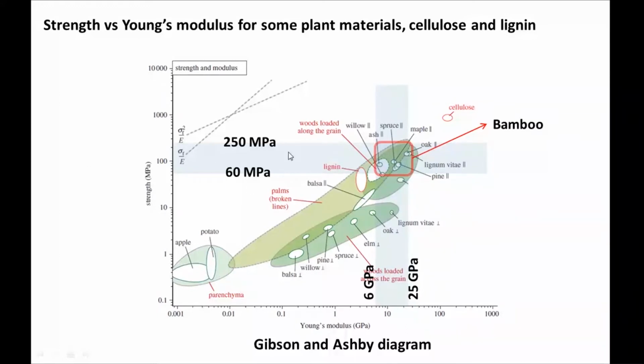And you have these 2 strips here, and that shows that the bamboo Young's modulus varies between 6 gigapascal to 25 gigapascal. It's the average. We have many different species of bamboo, and exactly it can be different. But on average, we can consider between 6 and 25 gigapascal. For the strength of the bamboo, we can consider 60 megapascal up to 250 megapascal. 250 megapascal for the tensile test, and 60 megapascal for the compression test that we will explain. I will explain why we have this difference. And you can see the good situation of bamboo regarding the other different types of woods, if you compare this region and this region.